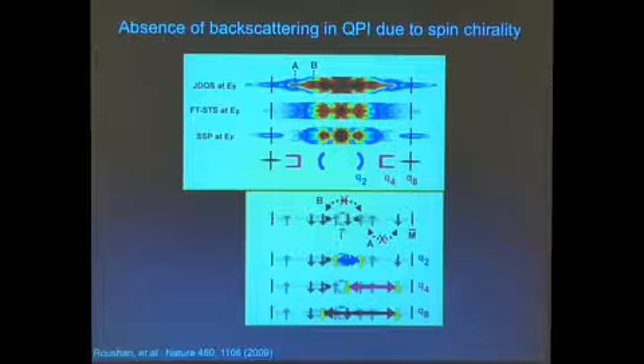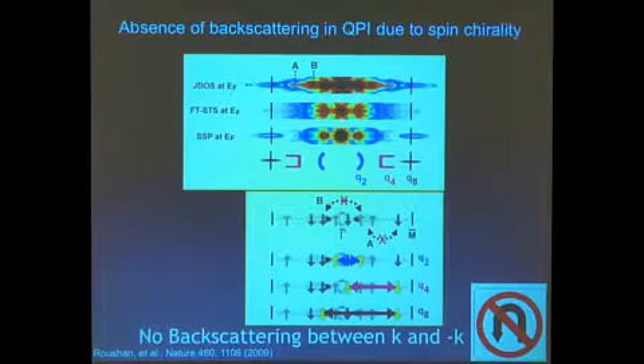So actually, this question of what the range of the potential is will be very important, and I'll show you that in a second. That actually has an effect that is quite important. Impurities don't flip spin. Well, in this case, we don't have anything magnetic in the sample. So bismuth antimony is... There could be spin-orbit coupling and things. Right. So this is actually one of the ways in which time reversal symmetry is not broken here. So that's basically what this experiment is showing us, is that this signal is missing because the impurities that you have here are non-magnetic, and that's what you would expect from this spin texture of the material.